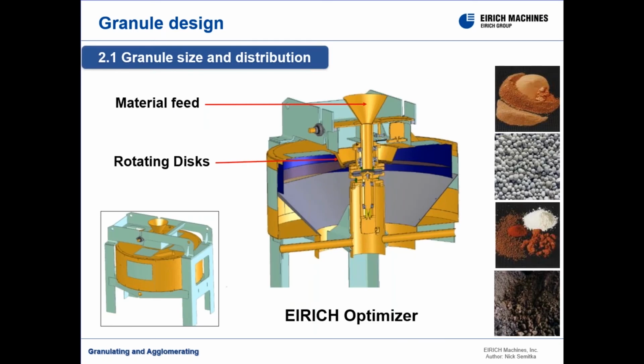You will never achieve 100% yields within a specific distribution. The oversized material needs to be screened, dried, and crushed before being put back into the system. Using an Eirich optimizer reduces the amount of product that has to be recirculated. We found that by implementing the optimizer, we are able to increase yields within a target range up to 90%